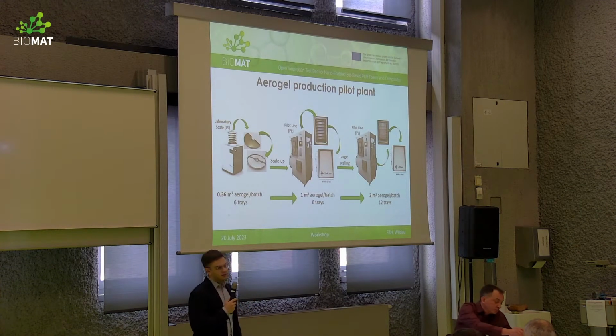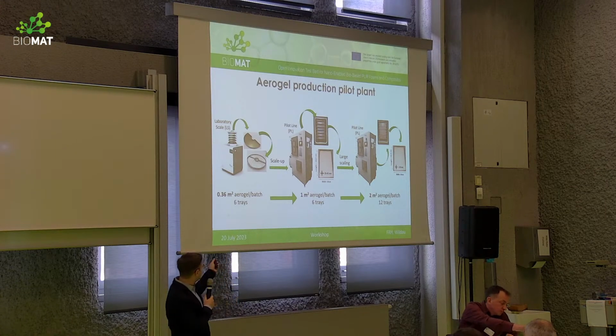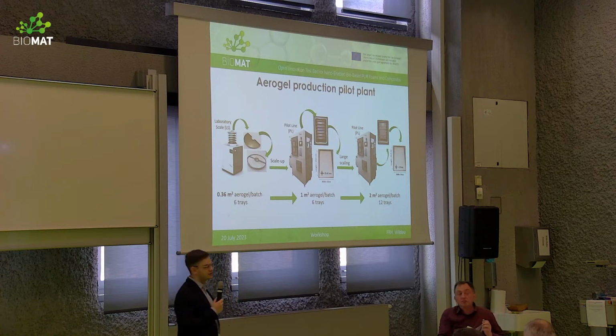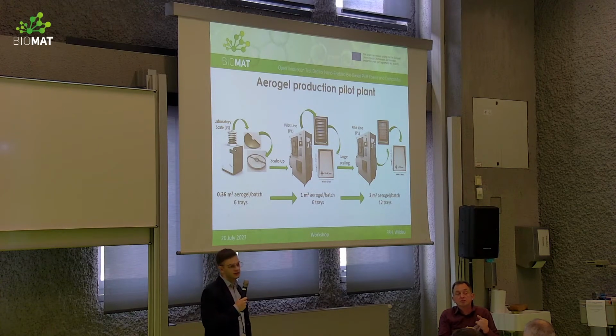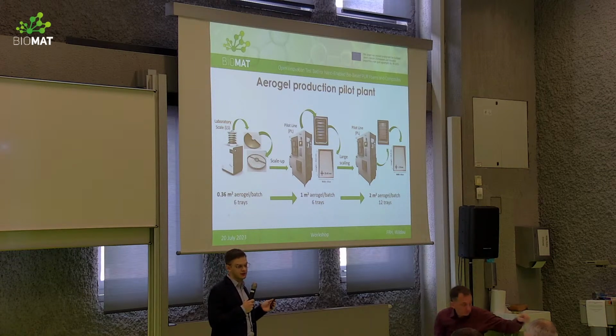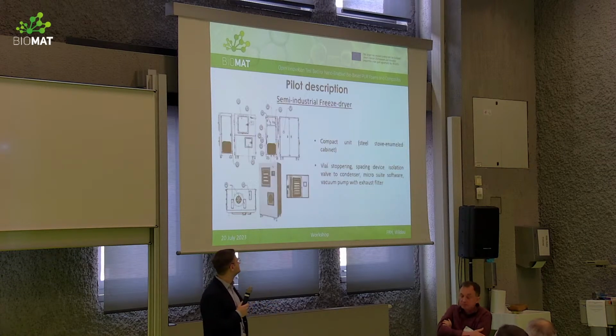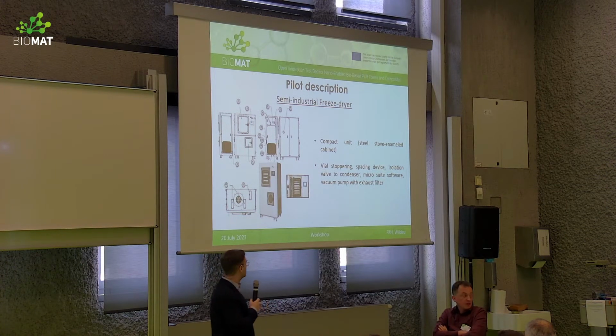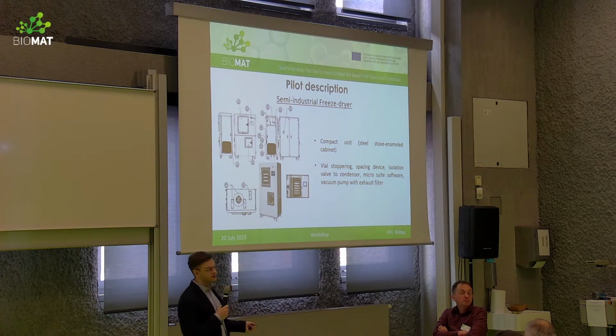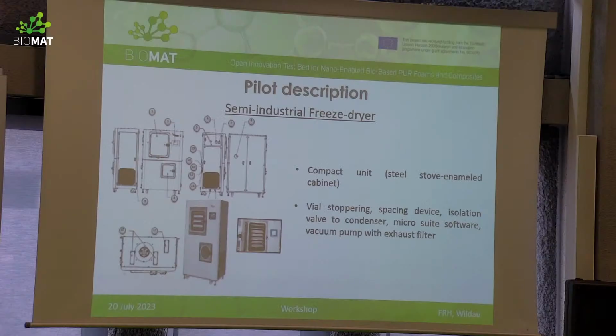Our pilot plant is able to go from 0.36 square meters of aerogel per batch up to 2 square meters by using the freeze dryer. It's important to note that this production will depend on the desired thickness of the resulting material. The pilot line consists of a semi-industrial freeze dryer, which is a compact unit with casters, constructed in a stainless steel cabinet. It has a vial stoppering and spacing device, an isolation valve to the condenser, a microsuite software, and a vacuum pump with an exhaust filter.